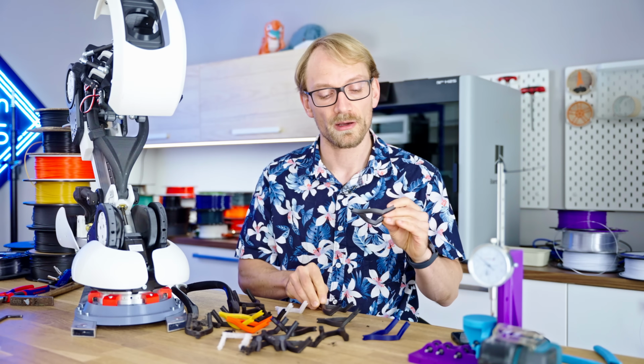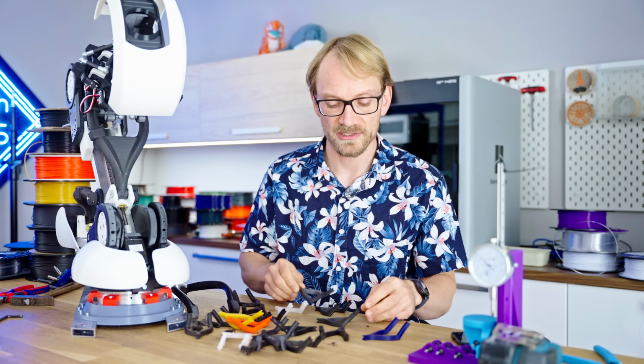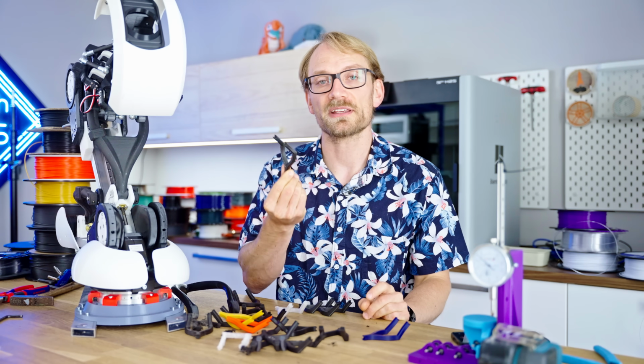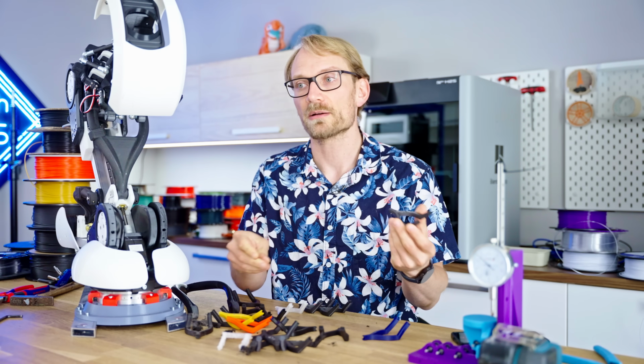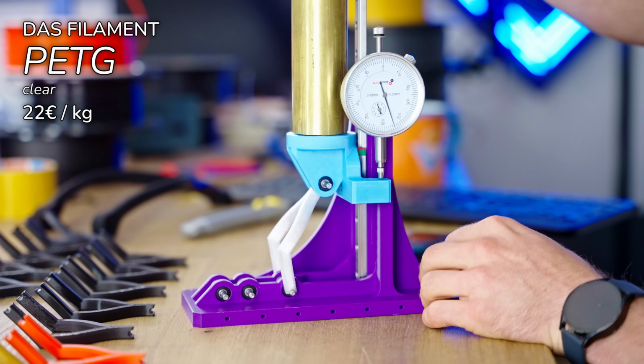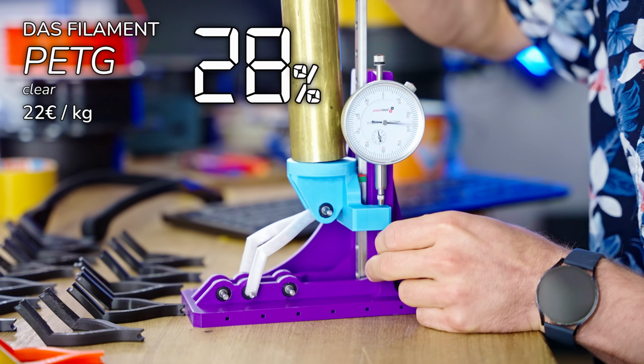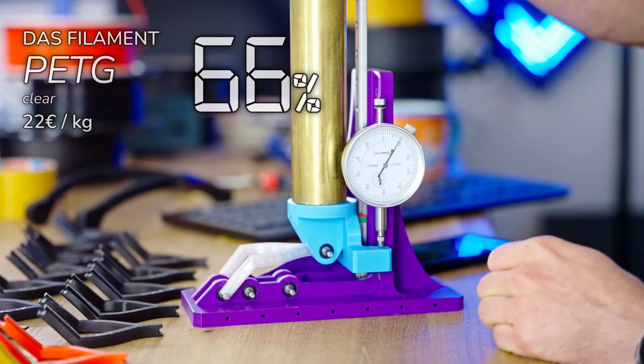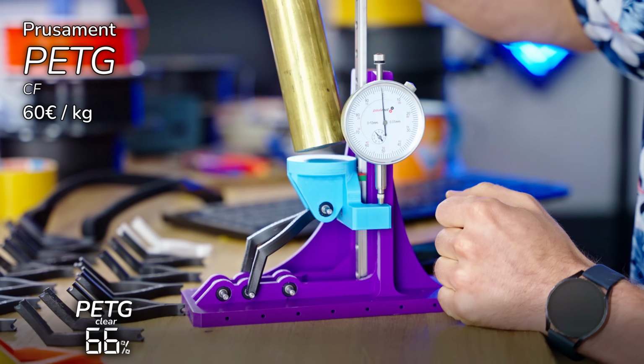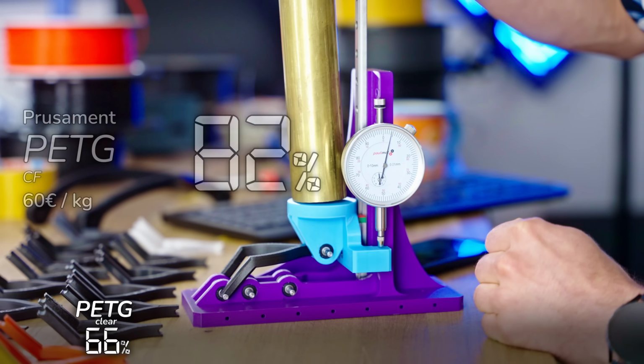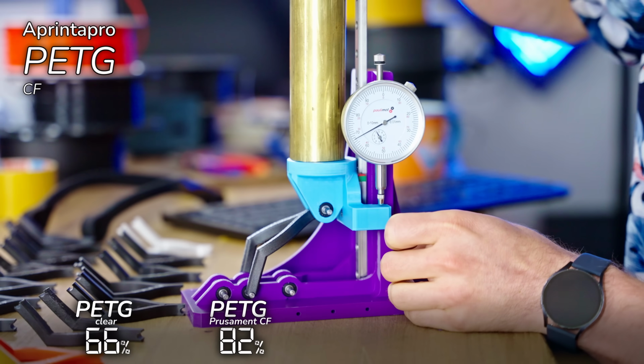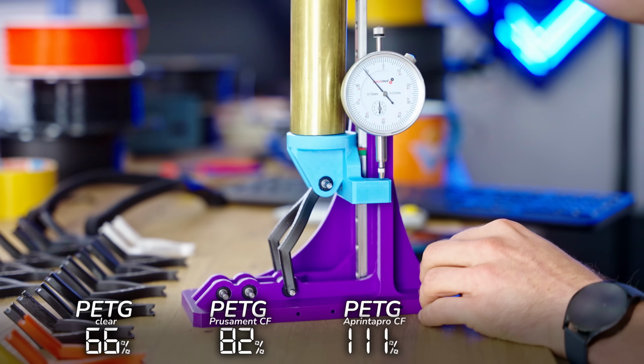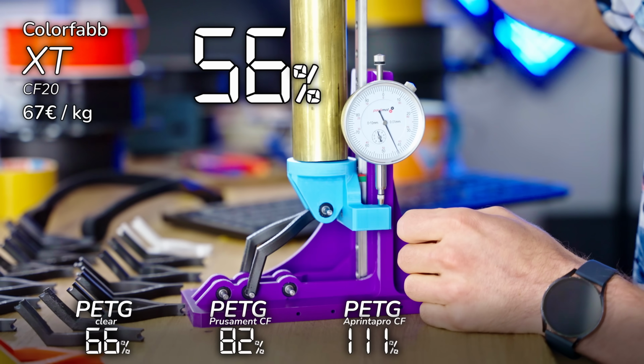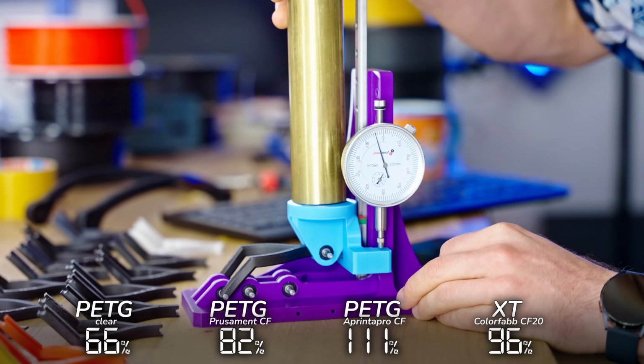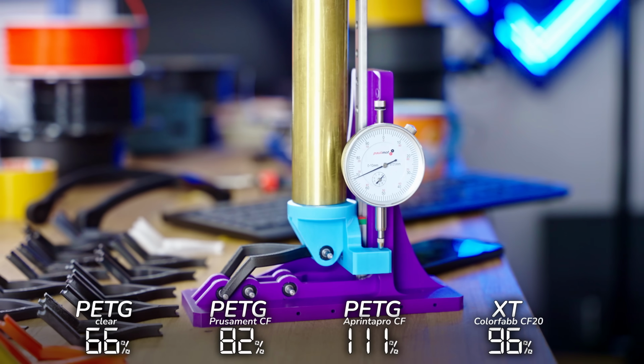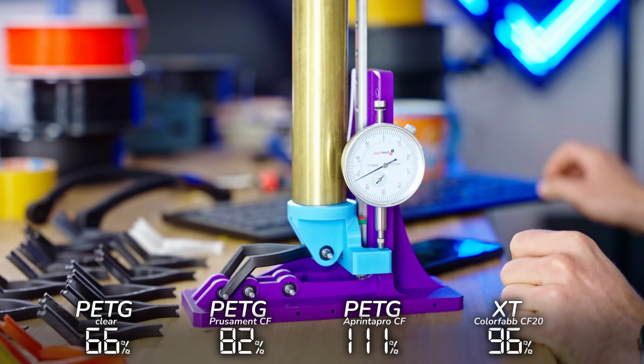One from Prusament, one from Aprintapro. They don't sell this anymore. And Colorfabb XT-CF20, which is also a polyester-based material. The part printed from plain PETG sets a new low score at just 66% of the median bend resistance. Prusa's PETG-CF gets 82%, the Aprintapro PETG-CF is 111%, and the Colorfabb XT-CF20 scores 96%. So even though these are carbon fiber reinforced filaments, they are still quite soft overall.